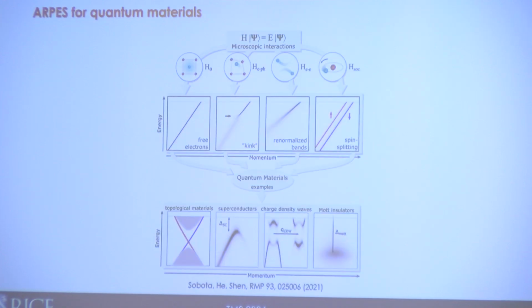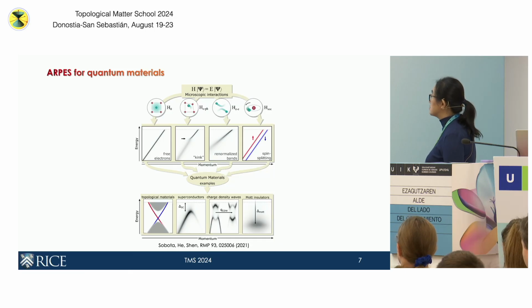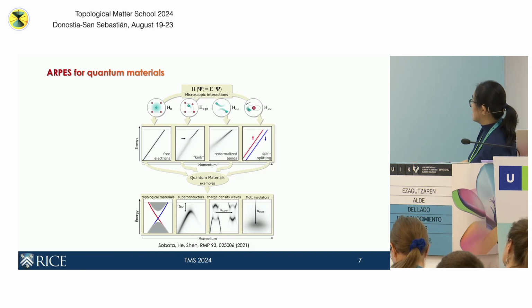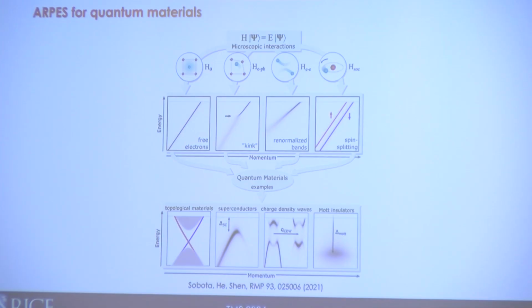Okay. So anything that modifies these A(k, omega) can be captured in our measurements. So we don't just measure the band dispersions, but we can measure a range of phenomena. For example, this is taken off a recent review of the ARPES technique. If you have a free electron dispersion that looks like this, we can, for example, look at the effect of electron-boson coupling, and this will basically produce a so-called kink in your dispersions.